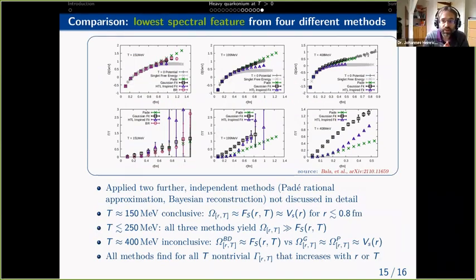So currently it's not yet totally unambiguous. If you look at this plot at 400 MeV here, you see that this HTL-based analysis gives you a result that is almost consistent for the real part with the singlet free energy, as it is usually used in the Debye-screened potential model calculations.